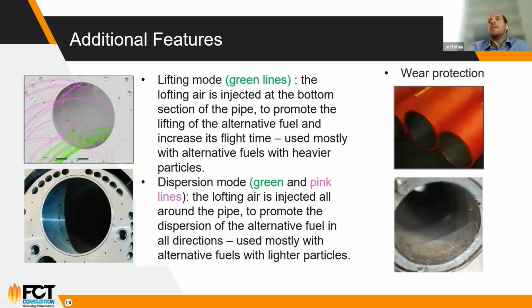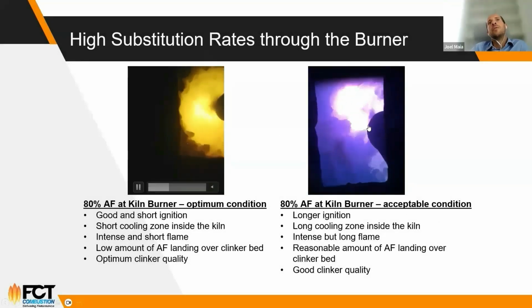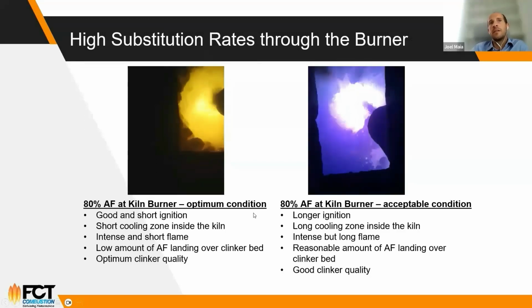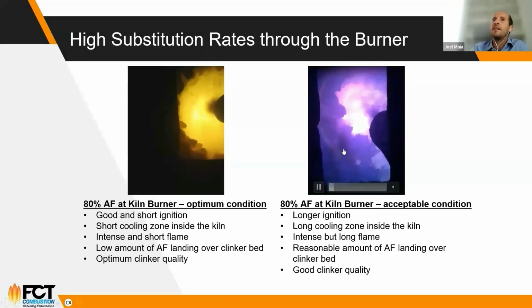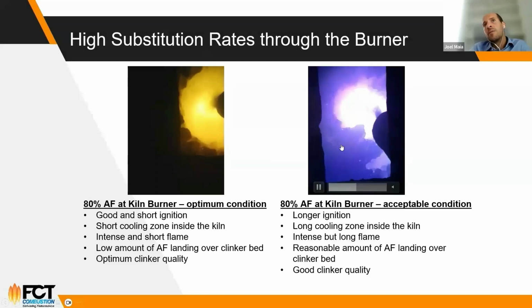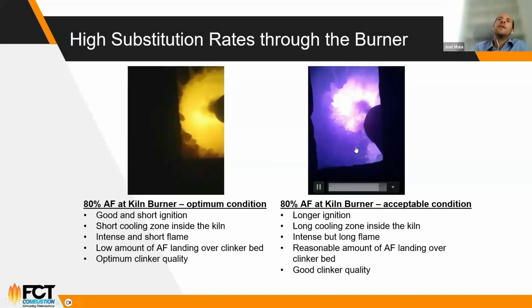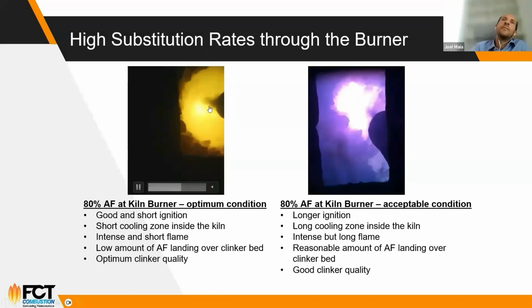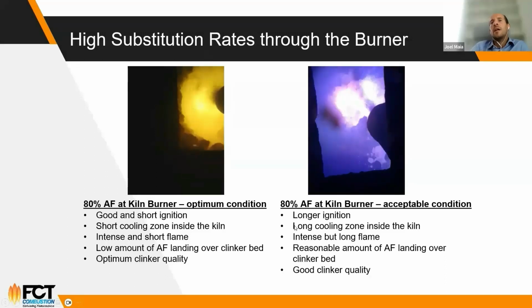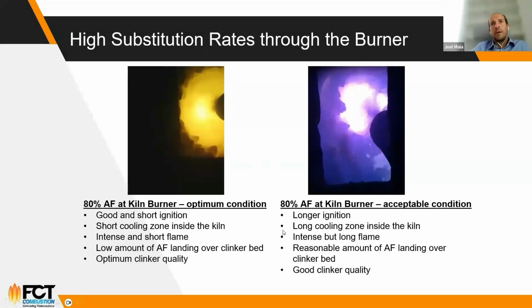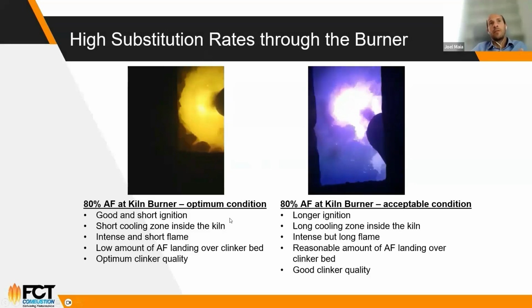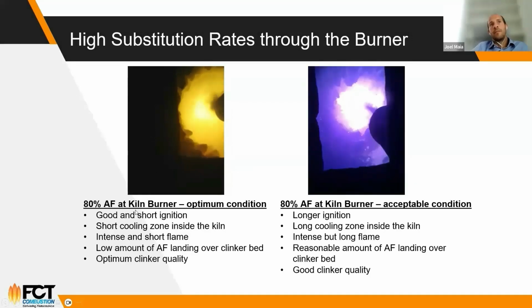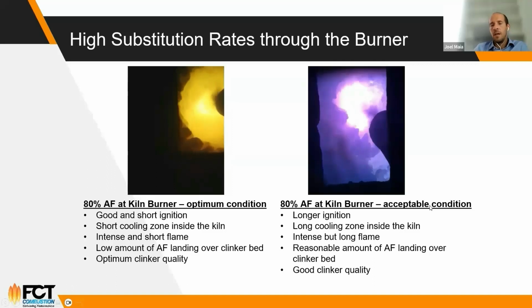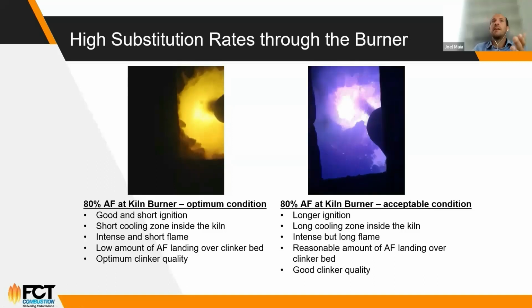And another feature would be, for example, wear protection. So inside the alternative fuel pipes, we can have some special material inside to minimize wear. Here we can see, last slide, two flames, both are with 80% alternative fuel, but you can see that the one on the left is a little bit better. On the right here, you can see some material falling onto the clinker and burning close to the walls and so on. You can see a much shorter ignition on the left side than on the right side and so on. Both kilns are running with 80% alternative fuel, RDF in both cases, and the remaining being petcoke in both cases, but the flame on the left is much more optimized than the flame on the right. I just wanted to show this to say that there is 80% and there is 80%.